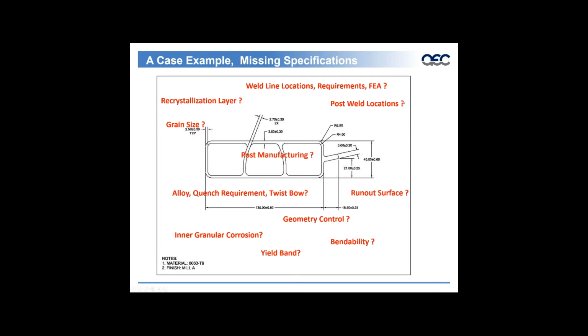Post-weld locations. Is there post-welding associated with this product? If so, we may not want a weld location where the post-weld actually starts and finishes. What is the post-manufacturing? What needs to be taken into consideration? How much machining will occur? There can be adjustments made in the mechanical properties and the microstructure associated with machining. Is grain size a concern? Recrystallization layer, as we talked about before. When we start specifying these items, and is there an IGC specification requirement? It starts to determine the alloy and it starts to determine the quench rate.